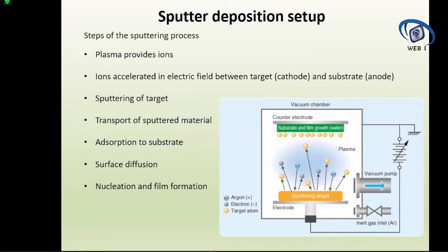The sputter system contains two electrodes. We have a target on one electrode, and on the other electrode we have the substrate, which is called the counter electrode. So the plasma provides ions. Ions are accelerated through the electric field, and they sputter material from the target, and that sputtered material is transported towards the substrate. While passing through the plasma, they have some reaction with the plasma species, or they adsorb to the substrate and diffuse into the substrate, and they form nucleation, and the film forms onto the substrate.